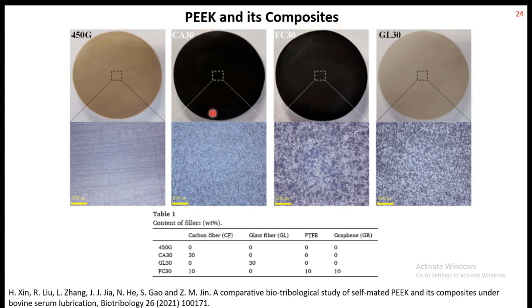The authors have tried different composites - one with carbon fiber, another with carbon fiber and graphene, and another with glass fiber, compared to pure PEEK material. The new thing they tried is sliding the polymeric part against itself - another polymer. So the pin is the polymer and the disc is also the polymer. The sliding is not taking place between polymer and metal or ceramic, but rather polymer against polymer. The idea is that this can give us an even lighter system, and also reduce or eliminate the problem of metal ions that I was talking about - metal ions getting released from the metal part, going inside our body and causing harm. So having both sides as polymer or polymeric material would be an advantage.